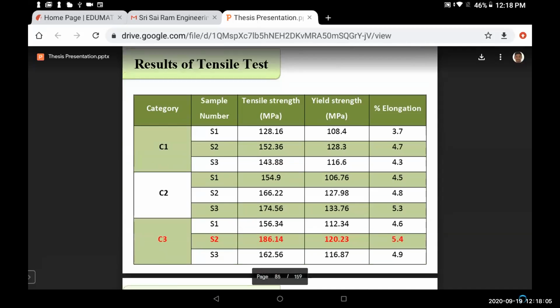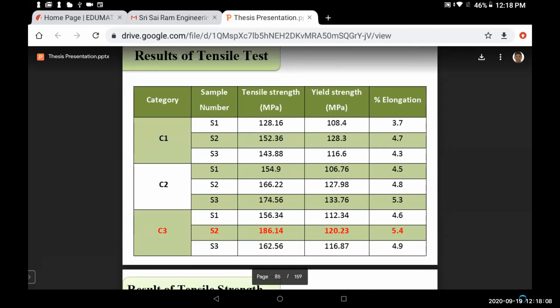Normally, a hybrid composite gives very high tensile strength or other mechanical properties, because it has the combined properties of both reinforcements. In this case, it has the properties of silicon carbide as well as multi-wall carbon nanotubes, which are available in C3. Out of these, C3S2, the category 3 containing aluminum with silicon carbide and multi-wall CNT, has a very high tensile strength of 186 megapascal with a yield strength of 120 megapascal. This is only due to the presence of multi-wall CNT along with the silicon carbide.